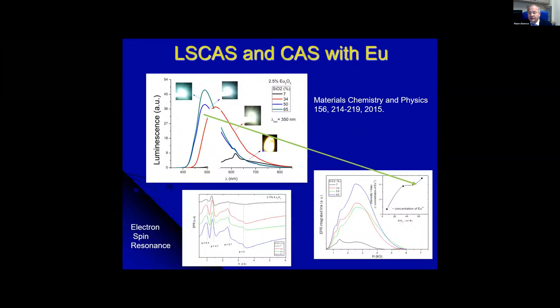Then of course, we tried to understand better the role of the glass composition in terms of the doping. We tried to use europium, because europium is also an important ion to get luminescence. We changed the glass composition from 7% of silicon up to 65% of silicon.